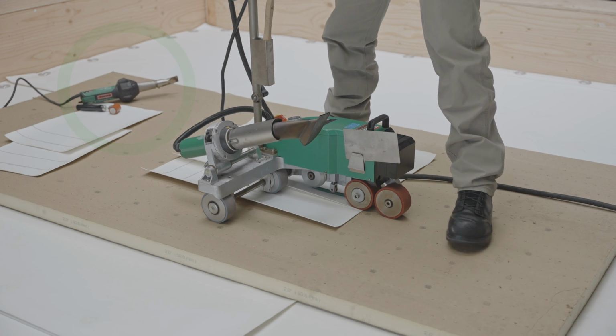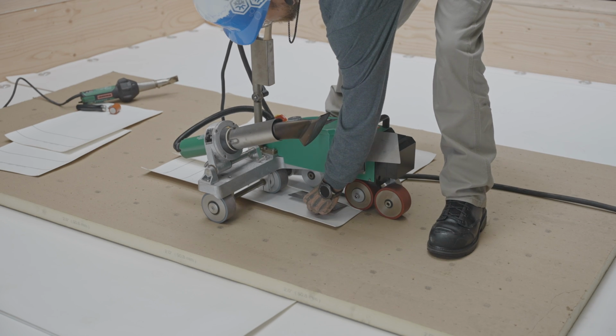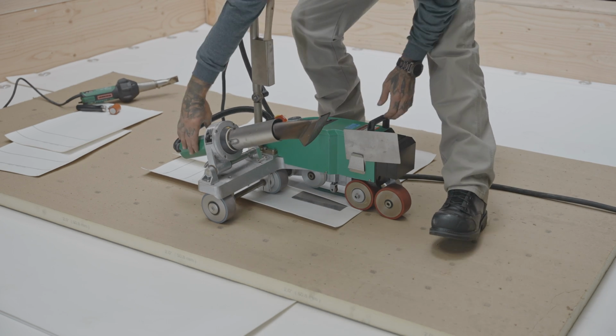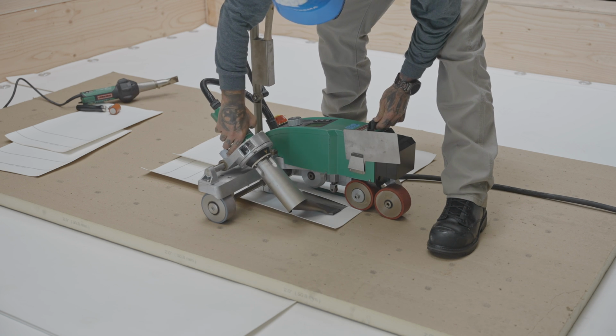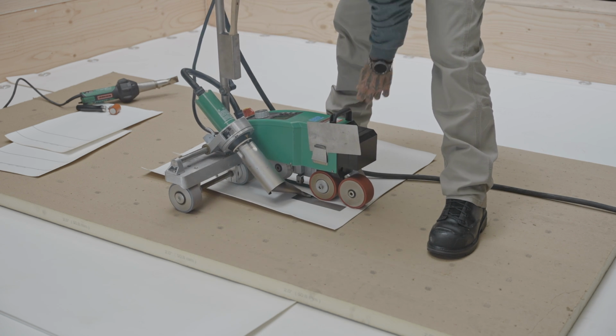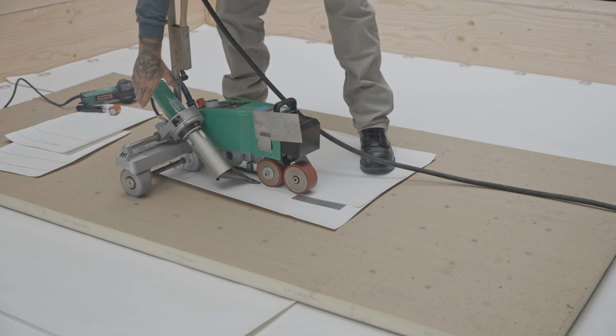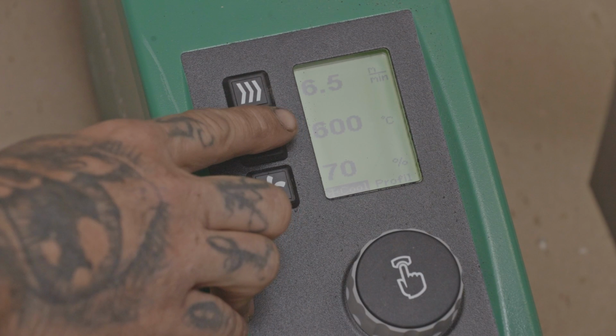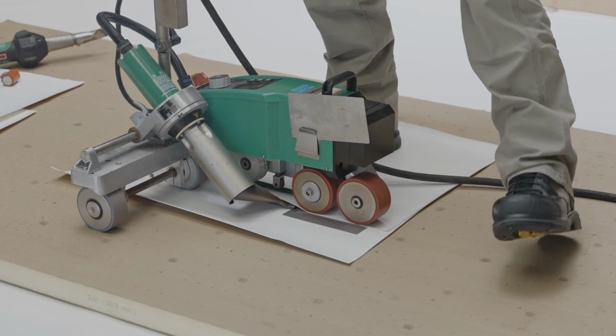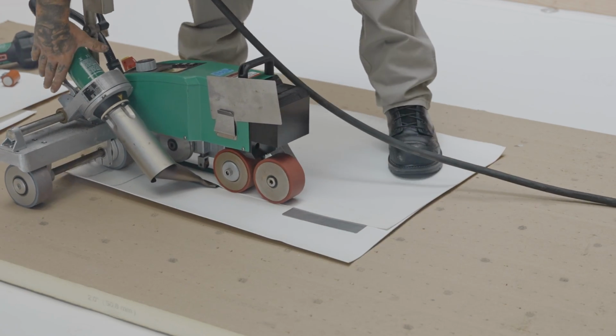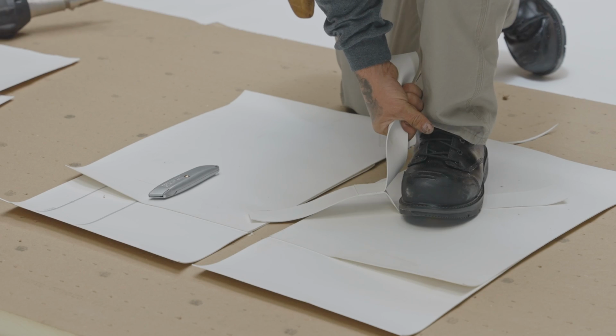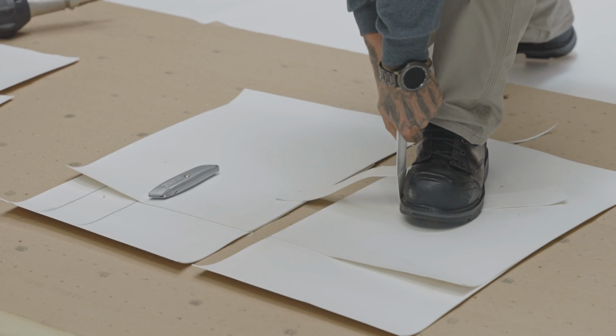The use of a welding cart and an electric hot air welder will be required. First of all, we recommend that you perform test welding each time your welding equipment is stopped and restarted, or when there is a change in climatic conditions. To do so, turn on your device and wait until it reaches the desired temperature. Use membrane scraps and weld them together. Once the sample has cooled, pull the two pieces of membrane apart.